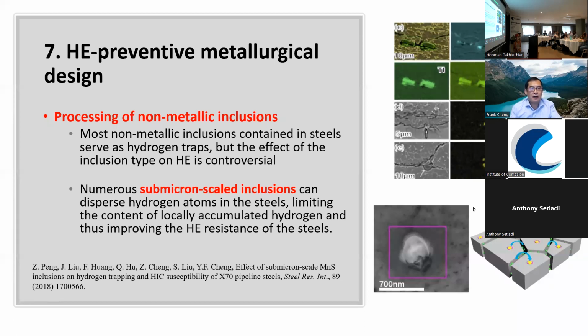And in terms of hydrogen prevention from the metallurgical design, I will speed up a little bit. There are many proposals to modify the pipeline steel metallurgical process, but a very common method is to process the non-metallic inclusions, because current research found that if the inclusions become sub-micron scale and uniformly distributed in the steel, it can decrease the local trapping of hydrogen atoms. Consequently, the concentration of hydrogen inside the steel goes to a very low level. So that's why hydrogen embrittlement can be reduced.